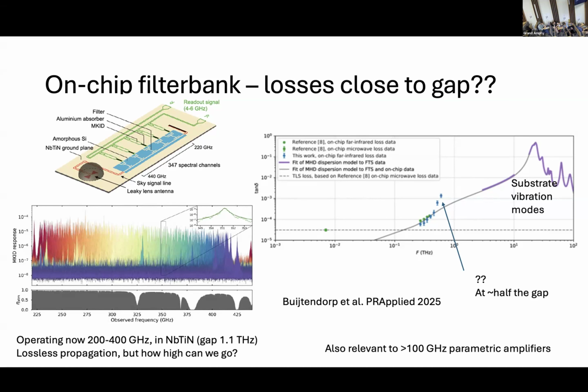So in this case, we expect that this radiation travels, from the superconducting perspective, lossless, and that we are typically limited by 2-level system type of problems, like we are at microwave frequencies. But remember that this is 100 times higher frequency, so it's also a bit of an unexplored range. And what you would see as an observation here is, if you do a frequency scan, in this case from 200 to 400 gigahertz, you see all these peaks coming up, and that's each resonator responding to a different color. So this is just the context of the technology.